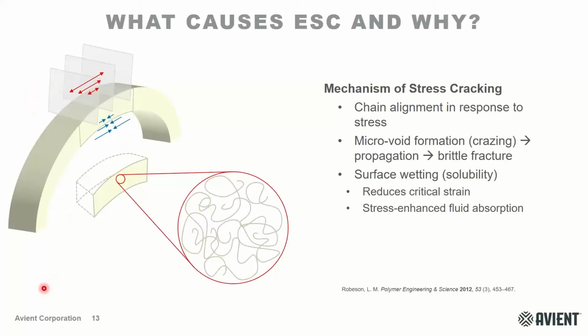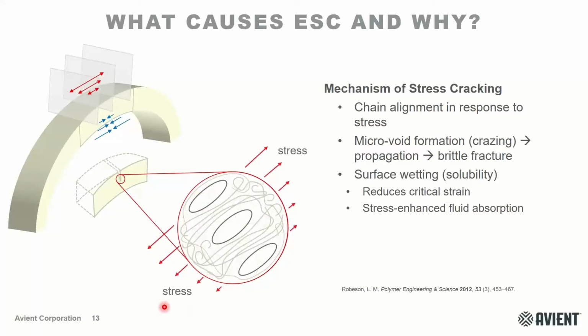And so what happens when you take a material and you apply a stress to it is that these chains that normally exist in somewhat of a random configuration or a random coil, maybe in a tensile bar a little bit more elongated than this, but what happens when you have that external applied stress is that those chains are going to start to align. They're going to have some mobility. They're going to be able to slide past one another and rotate, if it's within the critical strain of the material. And as those chains move around and reorient, what they'll do is that free volume, they'll leave behind a voided area, so microvoids.